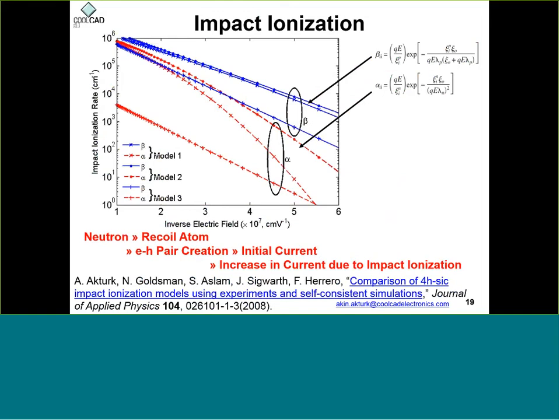So our initial preliminary data shows the failures are a result of some kind of burnout event. What happens is the primary neutron creates lots of electron hole pairs along its trajectory. It's about 1 square micron in area, so you have this track of electron hole pairs in a column, and it can be as long as several micrometers. And then you also have the high field because the device is in the off state. Because of this, you can have a lot of Joule heating within a very small volume, the J·E kind of heating.